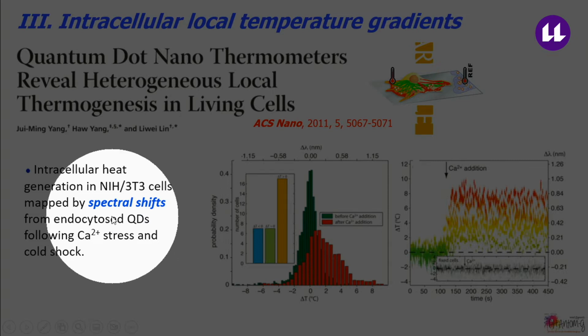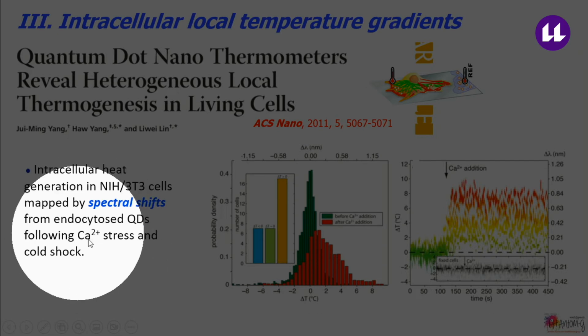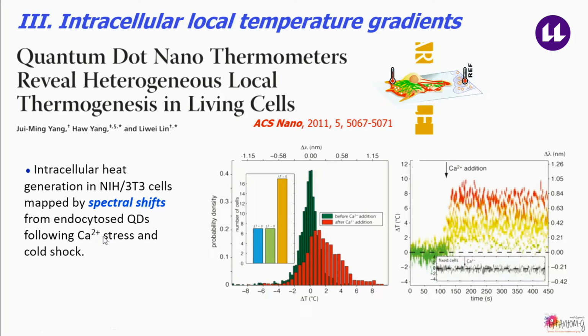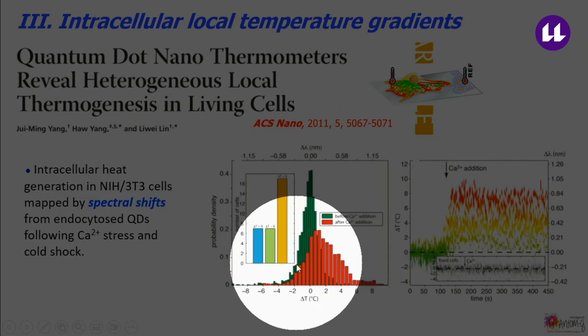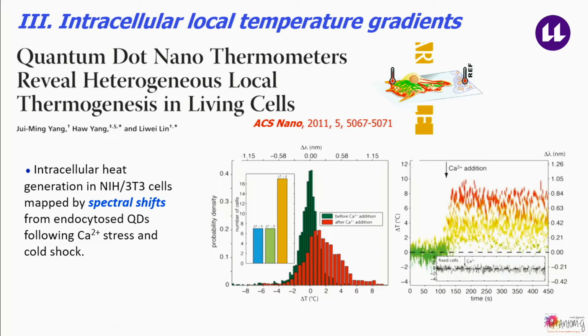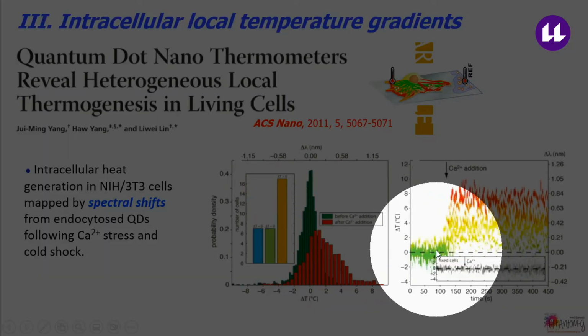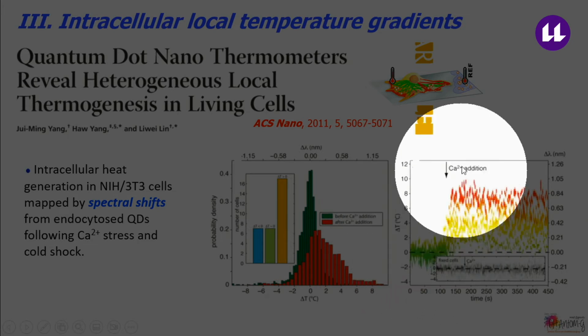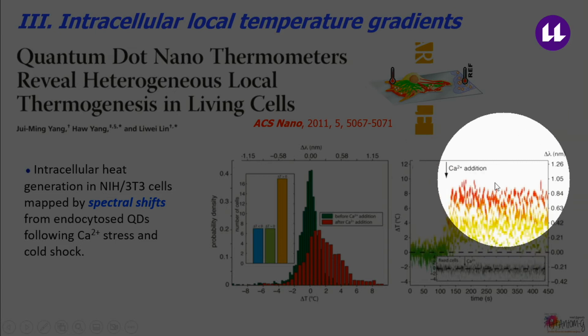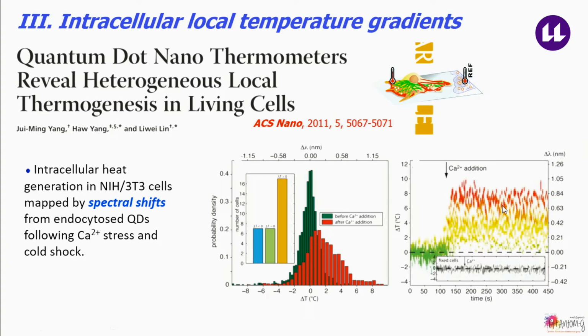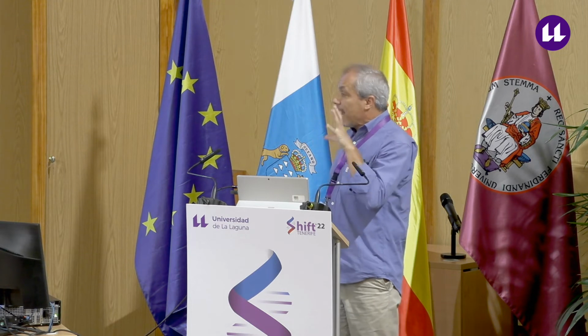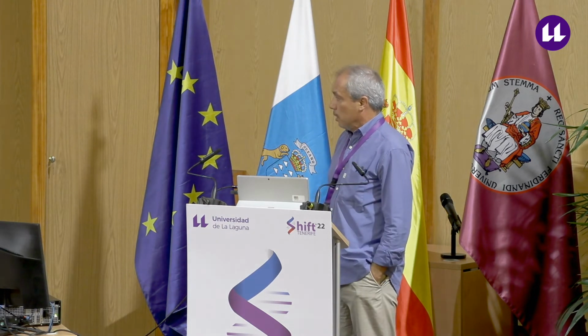they try to follow the increment of the temperature following calcium 2 plus stress, and also following a cold shock to the cells. So we have in these graphs the dispersion of the increment of temperature before and after the calcium addition, and we can see here that before calcium addition there is no increment of temperature, and then suddenly we have an increment reaching after a plateau, and this of course does not happen in fixed cells because that process does not occur. What I'd like to stress here is that there is an inhomogeneous intracellular temperature progression, okay?